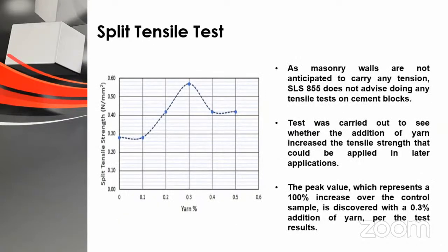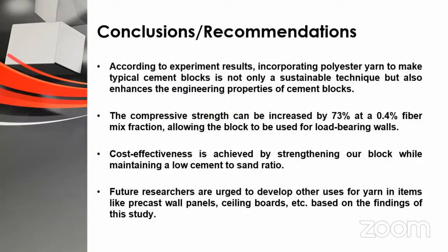Split tensile test. SLS 855 does not recommend conducting any tensile test on cement blocks, because masonry walls are not expected to carry any tension. Testing was done to determine whether adding yarn improved the tensile strength that could be used in future applications. As illustrated in the graph, the test result revealed that the 0.3% addition of yarn yields the highest value, which equals a 100% increase over the control sample. We have come to the end of our presentation.